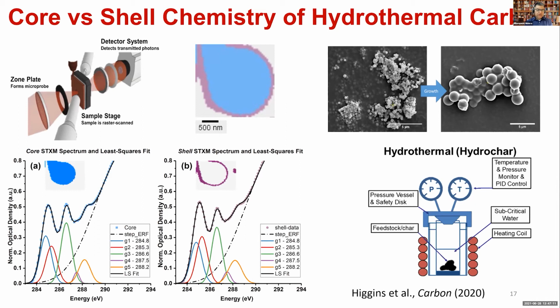The carbon to oxygen ratio remains the same in this material by XPS, but the way they bind in the shell versus the core is different. And you can see this STXM scan from the core versus the shell, and you can clearly see the difference in the peak ratio of the first two peaks for the core and the shell.